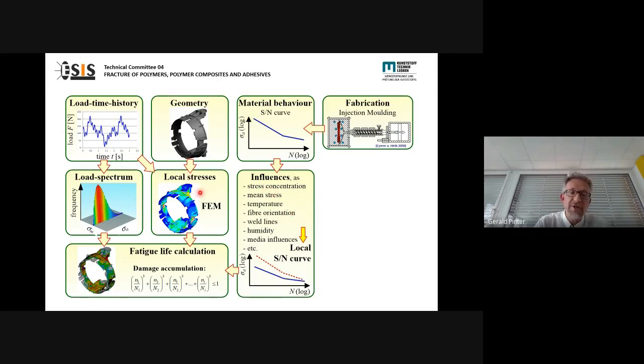Then you have the geometry and the local stresses. Based on that, you can do a FEM analysis. And you know the load history in the real components. Based on that, you do a conventional fatigue life calculation based on damage accumulation. So this is standard for metallic materials. And we have now tried to consider these for specifically short fiber reinforced polymers.